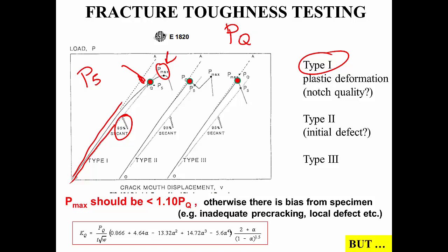I put subscript Q there because this is something that is under question, whether it is really a true result related to the fracture toughness. And I will keep this subscript for the fracture toughness in question as well. So for this first case, we take this 95% slope, the intersection with the curve, and we take that point as the failure point. Another possibility is, I will jump into the third case, where you have a straight line, it loads, there's a peak, and then there is a reduction of the load. In that case, there's no ambiguity.